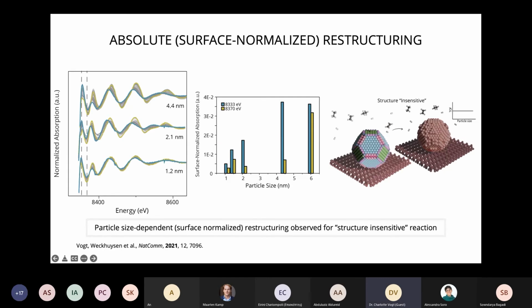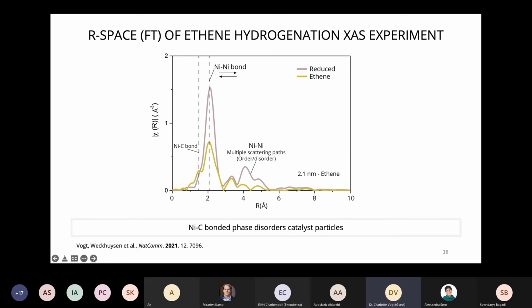If we take a Fourier transform of this left part of these spectra, we obtain more or less a radial distribution function of the average absorbing atom. So at about 2 angstroms, we can see the first nickel neighbor of the average absorbing atom. At 4 angstroms, we can see the nickel-nickel neighbor, the next nearest neighbor, multiple scattering pathways. This is a measure for order in the nanoparticle. If you see a peak at about 4 angstroms, that means that there is local order. And if you don't see it, that means that there's local disorder.